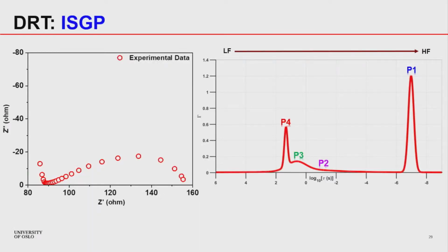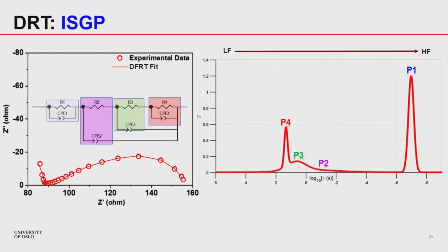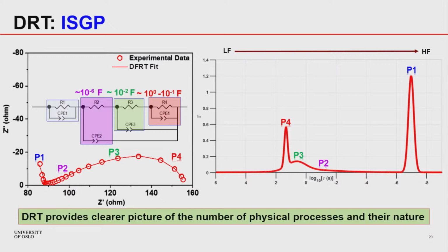Now, just to refresh, if I have this circuit, I should see 5 peaks in DRT, and if I have the other circuits, I should see 4 peaks in DRT. I took the experimental data again, ran the DRT, and what I see is that there are 4 peaks. This indicates that there is no Gerischer element. We don't need to complicate the system. Now the system is very simple, just 4 processes, where the first process corresponds to the ohmic part, and peak 2, peak 3, and peak 4 are responsible for the polarization resistance processes, which have typical capacitances of 10⁻⁶, 10⁻², and 10⁻¹, corresponding to the charge transfer and the mass transfer processes. So this exercise was just to see how you can get more information from the data.